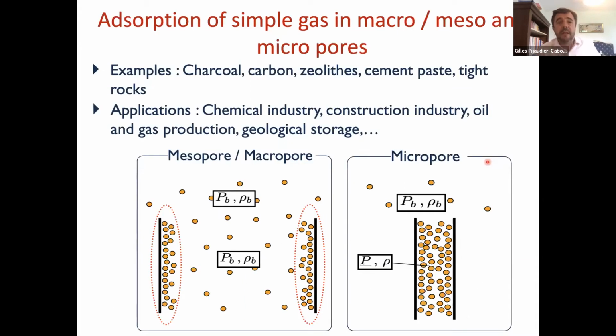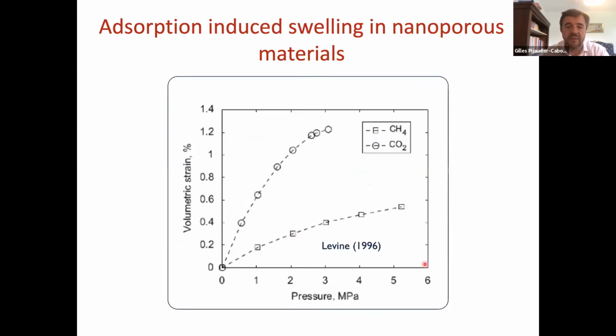A more complex example: the adsorption of a single gas in a porous solid, with many applications in industry - concerning carbon, but also cement paste, tight rocks, and many other porous materials. The issue is that in this case the fluid, which is in small pores compared to mesopores and macropores - micropores of a few nanometers at most - is confined by the solid phase, and is in a different state compared to the bulk fluid phase: different pressure, different mass density. And that produces a very unexpected response.